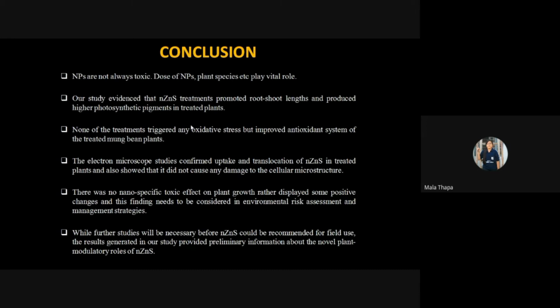The electron microscope studies confirmed uptake and translocation of zinc sulfide nanoparticle in treated plant and also showed that it did not cause any damage to the cellular microstructure. There was no nano-specific toxic effect on plant growth found, rather it displayed some positive changes, and this finding needs to be considered in environmental risk assessment and management strategies. But further studies will be necessary before using zinc sulfide in the field.